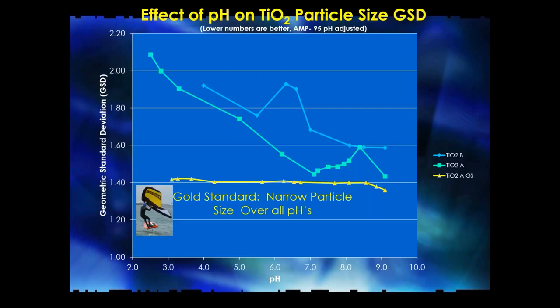You've got to make sure that the GSD remains stable over the pH range with all the pH additives that you use for making your paint. And so what we find here is that if we can grind at 83% solids, and then we let it down from there using a co-dispersant, a micro co-dispersant added in parts per million, we can do a fantastic job of stabilizing this and giving a great GSD over a broad pH range.